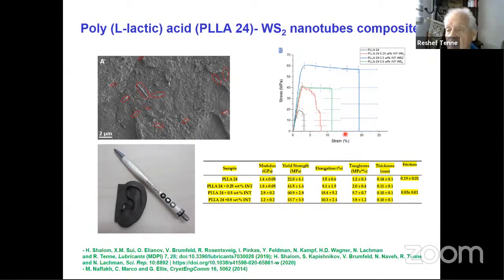So they are obviously weaker than carbon nanotubes, but in contrast to carbon nanotubes, they have a big advantage in three different areas. First of all, they are not toxic. This is very important because carbon nanotubes in the EU are now banned from many products due to toxicity. So here there is no issue of toxicity so far as we know. And there is, of course, room for many more studies on this. But so far, we know that these are non-toxic.